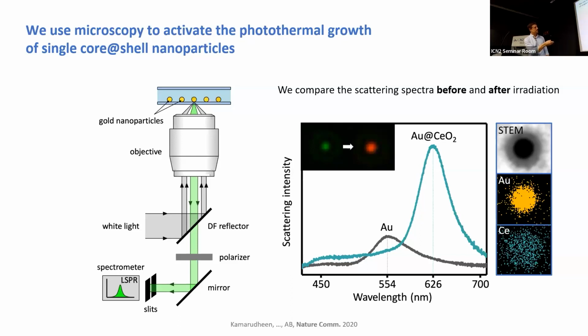Then you shine a laser for 50 minutes, and you look at the nanoparticle again, and it has turned into a red dot. And if you measure the plasmon resonance again, it's now at 626, and it's much stronger. And we did these experiments also on a TEM grid so that we could look at the nanoparticle after laser irradiation. And indeed, we can see that there is a ceria shell grown around it from EDX data.